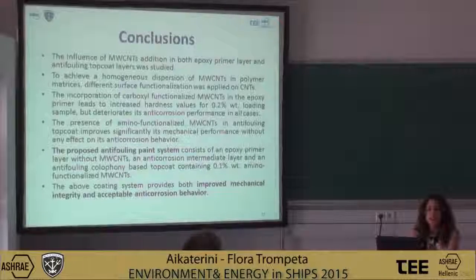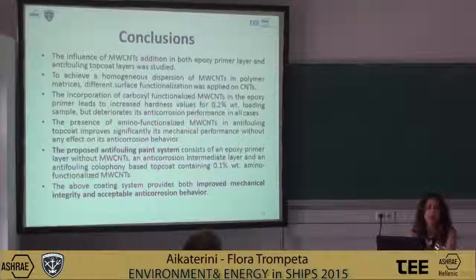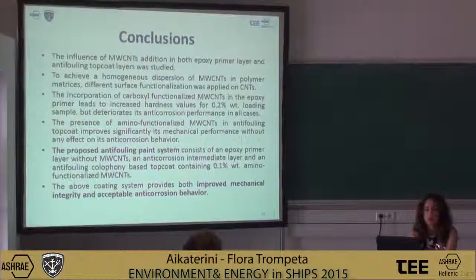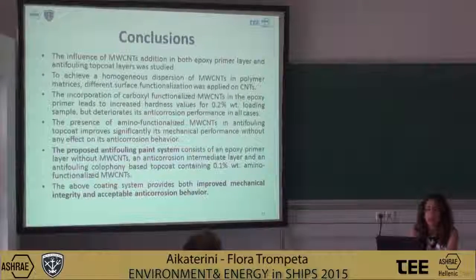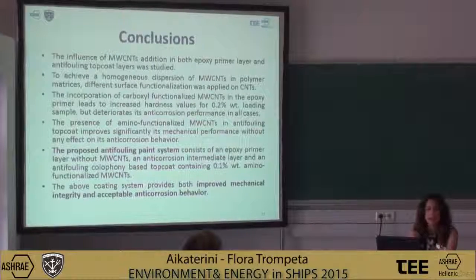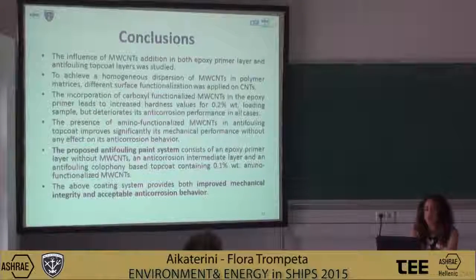So to conclude, the influence of MWCNTs addition in both epoxy primer and antifouling top coat layers was studied. To achieve a homogeneous dispersion of MWCNTs in polymer matrices, we used different surface functionalizations, and they were applied on CNTs. The incorporation of carboxyl functionalized CNTs in the epoxy primer led to increased hardness values for the concentration of 0.2%, but deteriorated its anti-corrosion performance in all cases.